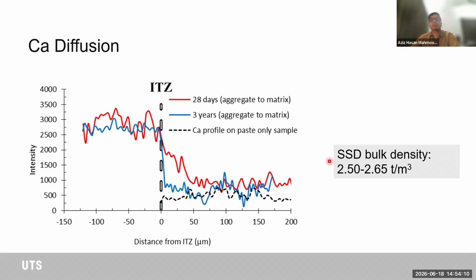And we also measured the bulk density of the units. So they ranged from 2.5 to 2.65 ton per meter cube, which sort of ticks all the boxes. So we did achieve the high density that we were targeting for. The calcium diffusion was there, so there's no risk of delayed expansion from the hydration of free lime. We had sufficient workable time to cast these armor units on site, and also we could leave these armor units on site for ambient curing even in cold winter nights.